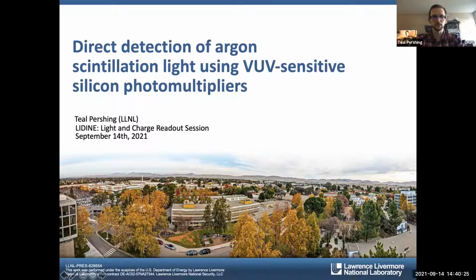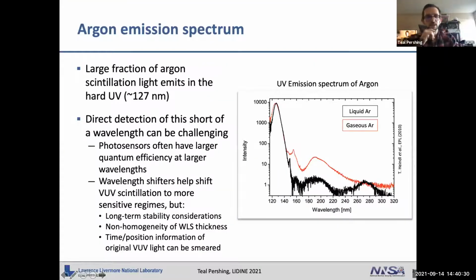A little bit of background on direct detection of argon scintillation light with these SiPMs. As we've seen a lot today, the majority of scintillation light from argon, when you have particle interactions in either the gas or the liquid phase, is primarily emitted in the hard UV, somewhere around 120 to 140 nanometers, as you can see from a past measurement on the right. And so direct detection of such a short wavelength is pretty tough.